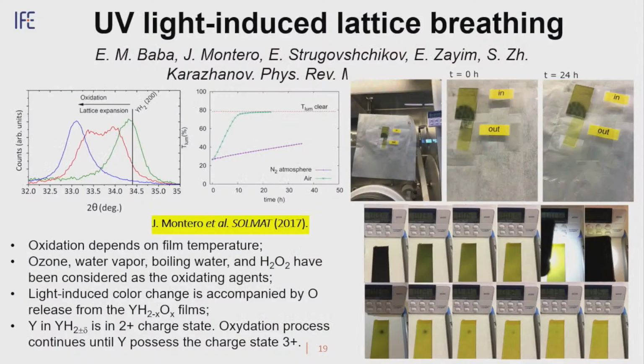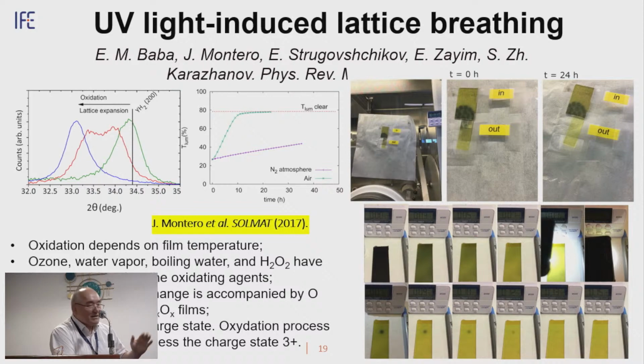It was not bleaching. Then what we did, we cut the sample into 2 pieces. One piece we kept inside the glove box, and the other one we placed outside. Then the one which is outside, it bleached very fast. Within just 20 minutes, it was bleaching. And the one which is inside, it was still there. So then we found, oh, this is something very interesting. So we clarified here that the lattice is breathing somehow, but we didn't have direct proof for that.